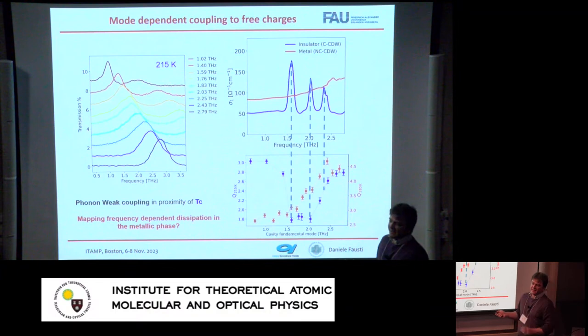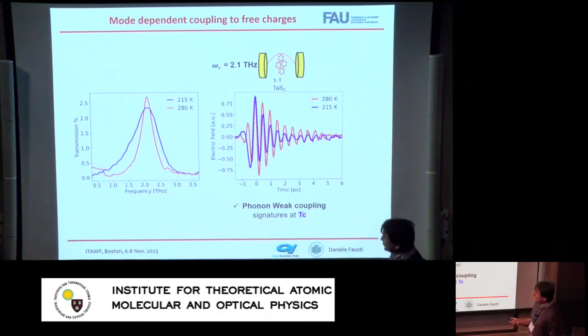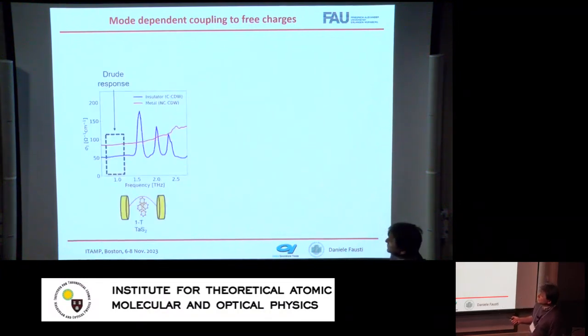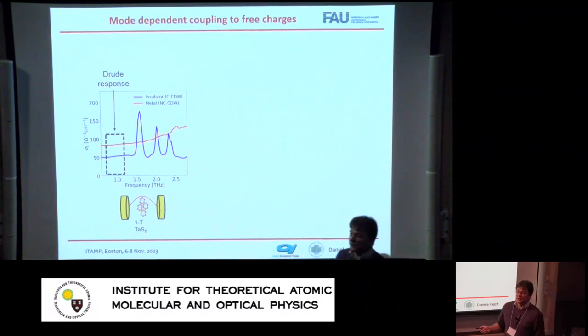And so in some sense the cavity allows me to measure the dissipation of phonon modes, which I don't see. So that's inside the hysteresis cycle that you see this? No, outside the hysteresis cycle, above, yes. That's the peculiarity.